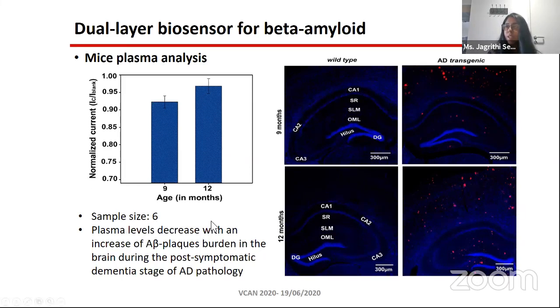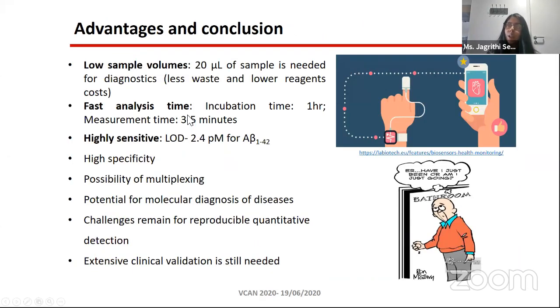The reason for that is because plasma levels decrease with the increase in A beta plaque burden in the brain during the post-symptomatic dementia state of AD pathology. So if you look at the brain scans, these are the immunohistochemistry results. It shows that the amyloid beta plaques increase from 9 to 12-month-old, and correspondingly, the presence of beta amyloid in the blood decreases with the increase in age. So they were correlated.